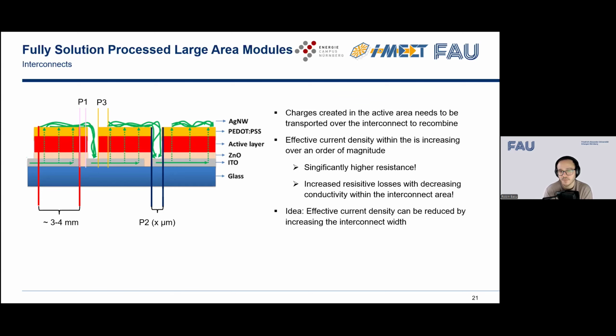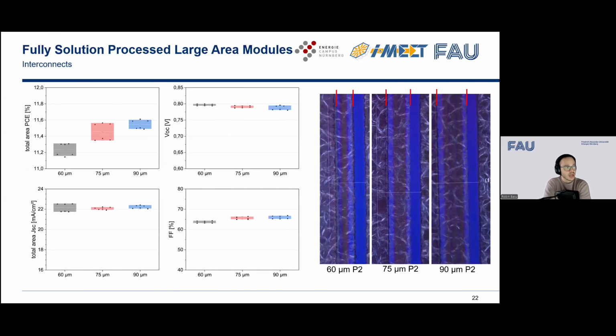So that also means that you have a significantly increased resistance within it, because all of the charges have to pass through the interconnect that is a lot thinner than the active area. So we came up with the idea to reduce the current density within the interconnect by adjusting the width of the P2 line, which is the interconnecting layer. And what we found is that if we increase the width, we can efficiently increase the fill factor of our devices by simply ablating a little bit more. And we can even get higher efficiencies on the total area, because the reduction in geometric fill factor is not as big as the improvement in fill factor that you get from it.